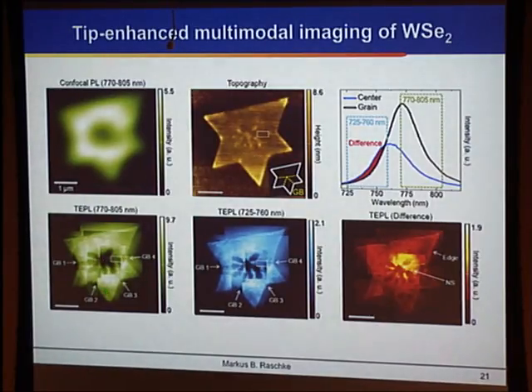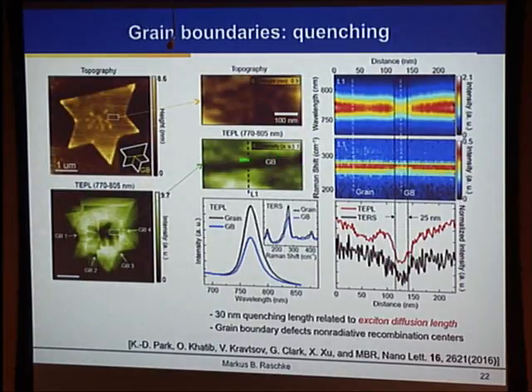And then we can zoom into these images and look specifically at the grain boundaries. So here is a high resolution near-field scan. And what you see, for example, in looking at the grain boundaries, is a decrease in the photoluminescent yield. And we can resolve the width of this effect along one of those grain boundaries. And we see this is about a 30 nanometer channel, over which we see this quenching of the photoluminescence. We see no change in the Raman response.